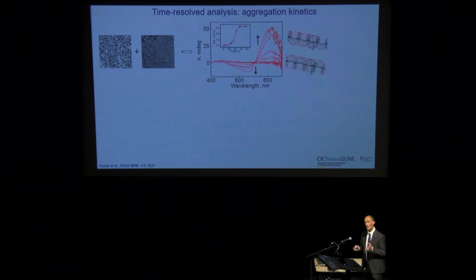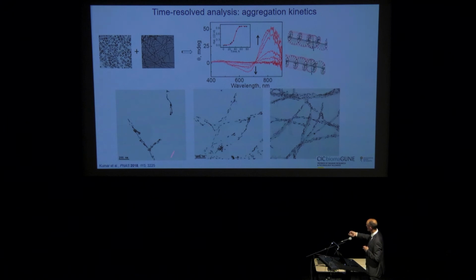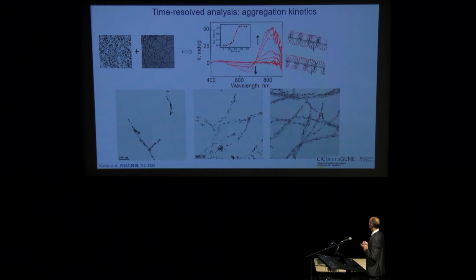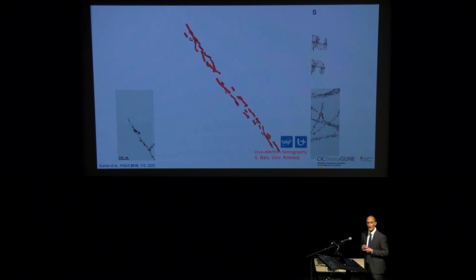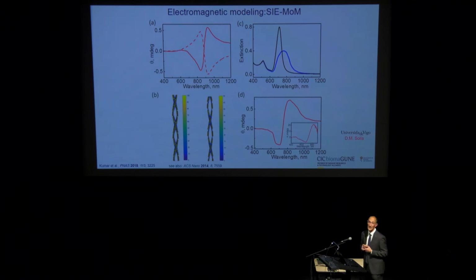that show that something is going on that now promotes chiral interaction between circular polarized light and the assemblies of the gold nanorods. If you look in the electron microscope, you actually see that over time, there are longer and longer arrays of nanorods that somehow seem to follow the direction of these fibers. And then our colleagues again in Antwerp were able to do cryo-electron tomography and show that indeed there is a sort of double helical organization of the nanorods that explains the optical activity that we see. And it can also be explained because we can now do modeling that shows that similar arrays would give also optical activity similar to what we see experimentally.